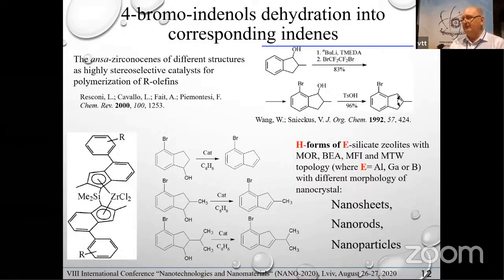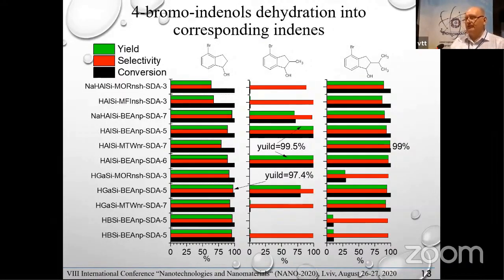For example, for preparation of a new generation of stereoselective catalysts for olefin polymerization, last year I used ansa-zirconocene, and for preparation of some zirconocene catalysts, it is necessary to make a very accurate and selective dehydration of bromo-substituted indenols into the corresponding indene. We tested different zeolites with different compositions and different acidity, and can show that in all cases, depending on the substrate which needs to be transformed, a different zeolite with different acidity, especially different strength of acid centers, can be used, and the result can be a very high yield of the desired compounds.